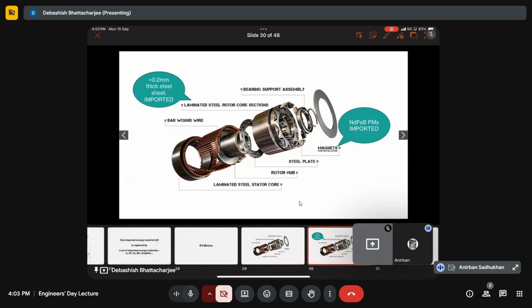When motors need to be rotating at high speed, these stampings need to be thinner and thinner, and of a chemistry that reduces loss. If these stampings are thick, then there is a resistance loss because of it. This is fundamental high school level understanding of Ohm's law. So you make these laminations as thin as possible. As the motors need to go to higher and higher revolutions per minute, as the RPM goes up, you need to prevent loss in the motor. You need to make thickness as small as possible.